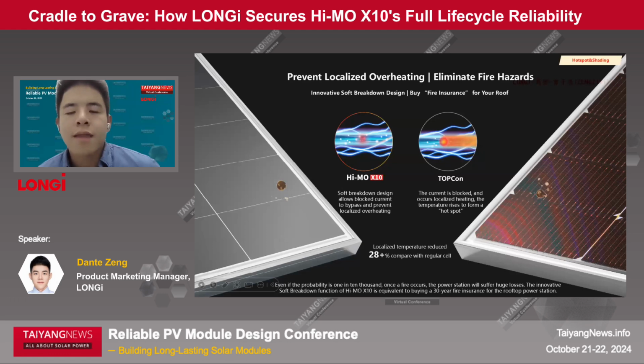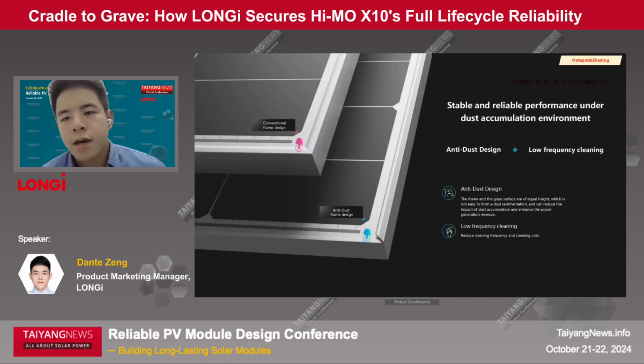And also for the temperature, I think the power loss is just one part, but the temperature really threatens people's safety and also your economic safety. For traditional modules, the maximum hotspot temperature could reach more than 170. And for our Hi-MO X10, with our HPBC second generation cells, we can reduce the temperature by more than 28%, which in real numbers means we can bring the maximum hotspot temperature down to about 110 or below. There is about a 60 Celsius temperature gap, and this gap largely reduces the risk coming from shading and guarantees customer safety.